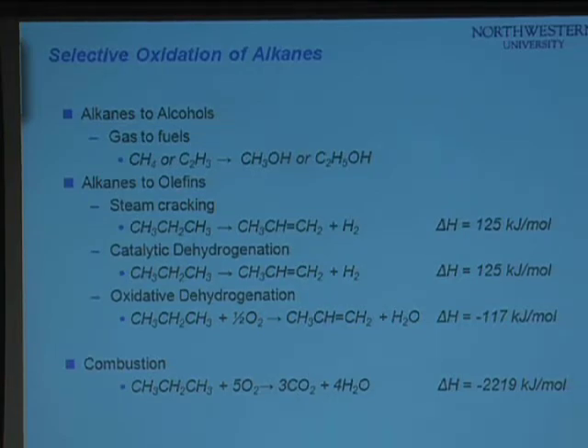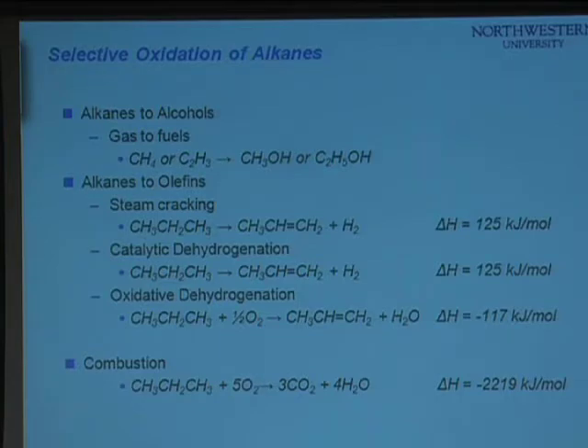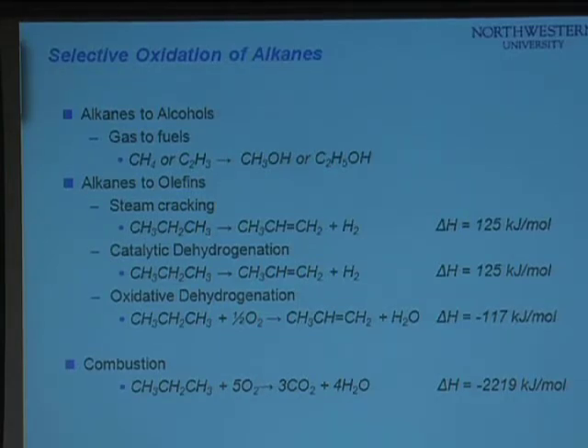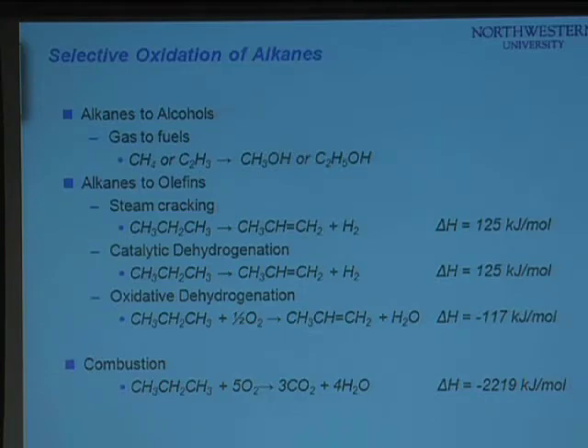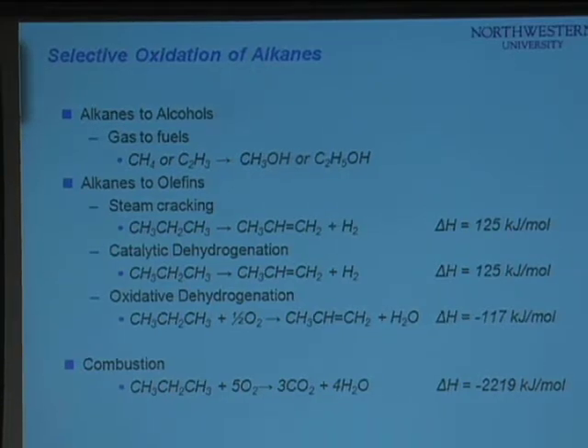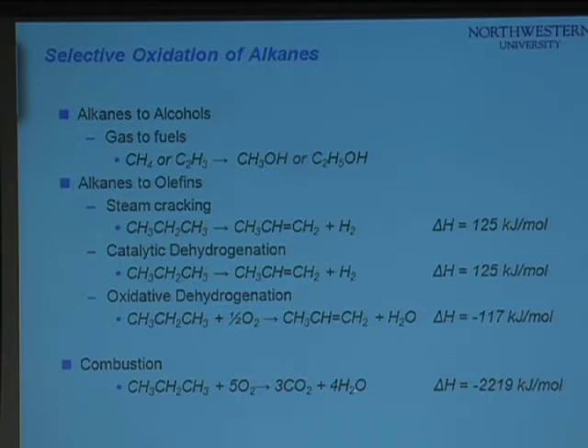Another kind of selective oxidation is to convert alkanes to olefins. There's a huge demand for olefins, particularly polypropylene, and there isn't enough supply. The growth in demand for olefins will outstrip almost everything else. Right now it's done by cracking, a very energy-intensive endothermic process. If we could do it oxidatively — couple oxidation to this process — we can make it exothermic, so we don't have to burn fuel to make it occur. The problem is that instead of making olefins, what normally happens is combustion. We need a catalyst to create a selective process.